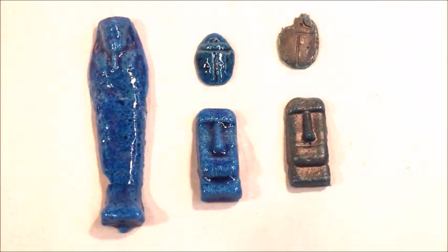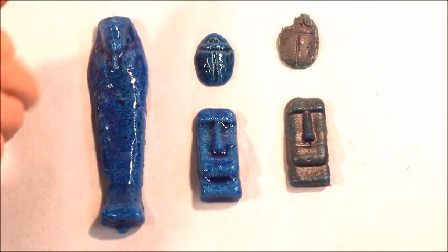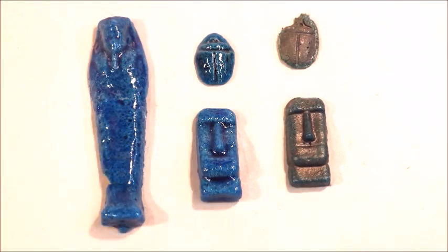Now, the only thing I'm going to add to this, and then I'm through, is as you mold this up from the dough-like, clay-like state you saw the other day where I wrinkled it around in my hands, it's crumbly. I've got one of these in the plastic mold now. I don't know when I'm going to get it out. It feels like it might break before I can get it out. But I'm going to experiment with adding more ball clay to see if I can get some increased plasticity and make it more pliable. And hopefully it will be easier to work with, and it won't affect the glaze, because at this point the glaze color is what we're after.